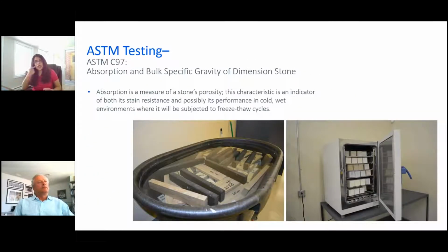So ASTM C97, that's the absorption and the bulk specific gravity of dimension stone. So the absorption is the measure of stone's porosity. This characteristic is an indicator of both its stain resistance and possibly its performance in a cold, wet environment where it will be subjected to freeze-thaw cycles. This test also gives us the density of the stone, which is used in all our calculations whenever either the stone is stacked or individually load-bearing connections are used for those applications.